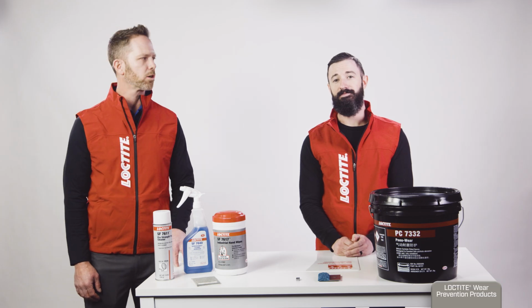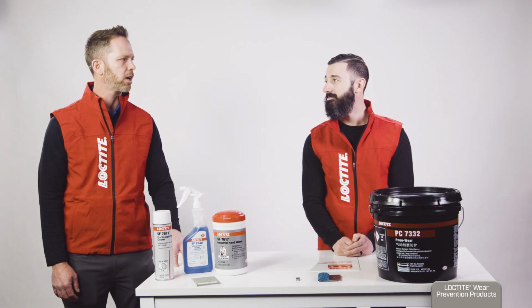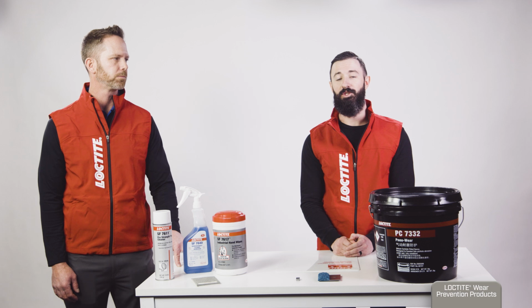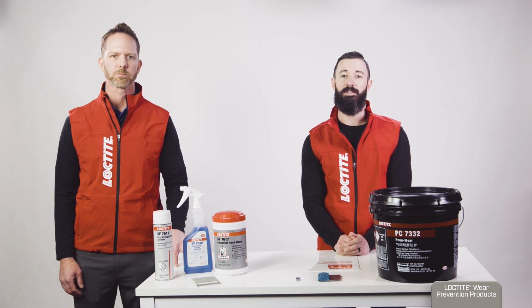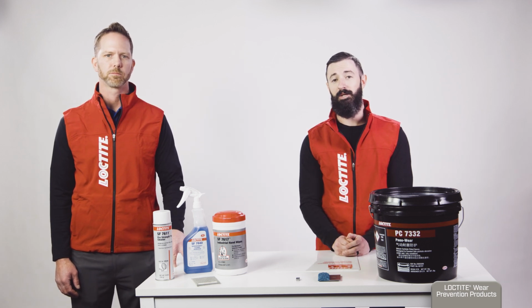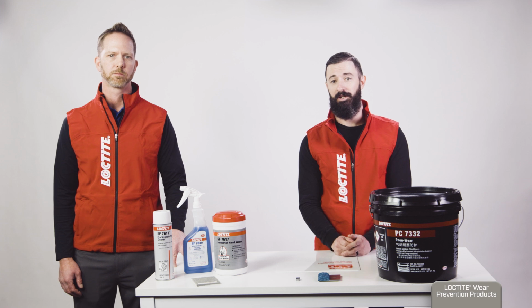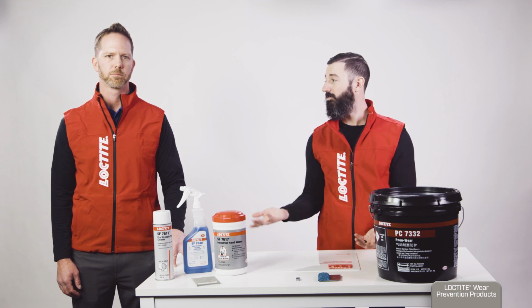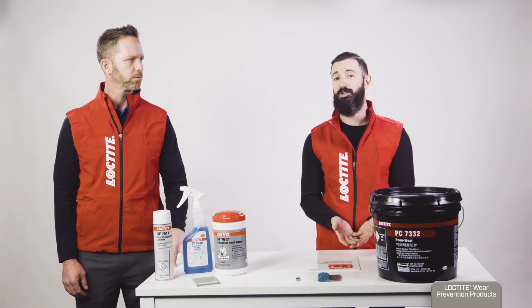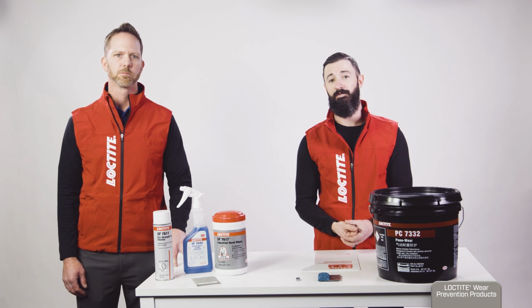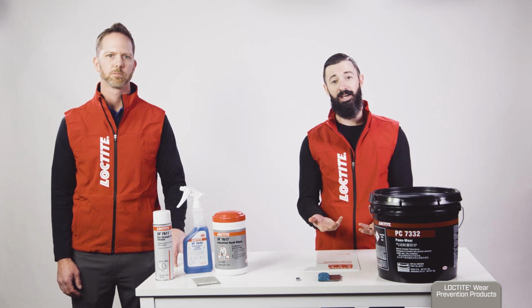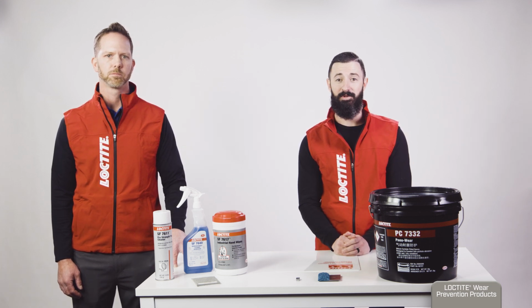And how long is the cure for Loctite PC9593, Matt? That's a great question, Keith, and always a very important one that our customers ask. The cure time ranges based on ambient temperature and surface temperature. But on average, as you mentioned before, 4 hours is our fastest curing product. This product does meet that 4-hour profile. So because of that, this has caused the product to become very popular.